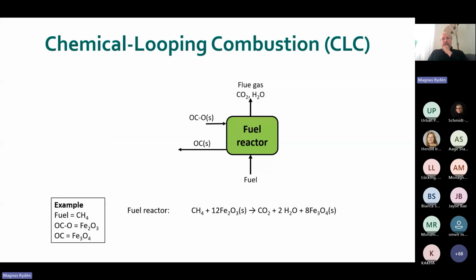So let's use simple gases and oxygen carriers as an example. Fuel, in this case, we use methane, and the oxygen carrier would be hematite. That's simple iron oxide in this case. At suitable conditions, if we have a temperature of, say, 900 degrees, then the fuel will actually react with the oxygen carrier and form carbon dioxide and steam. And we will also then get a reduced oxygen carrier, in this case, magnetite.